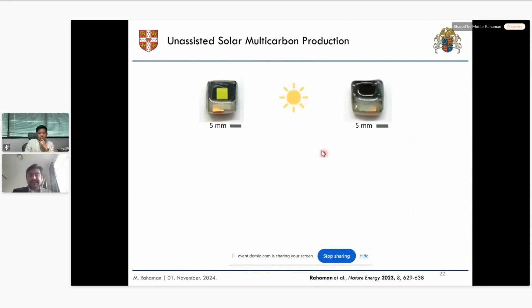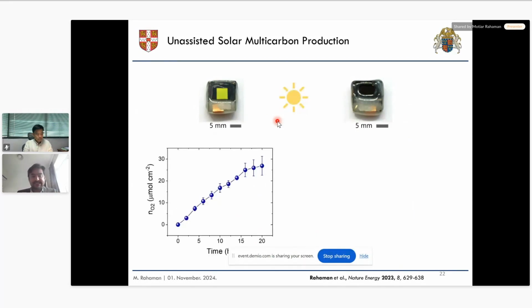So this is how it looks. This is the bismuth vanadate side, where we have the water oxidation. This is the catalyst side. It's quite black. It's the catalyst attached to the perovskite solar light absorber. So these are just two different sides of the same device. We just immerse this standalone device into CO2-saturated water. We just shine light, and then this happens.